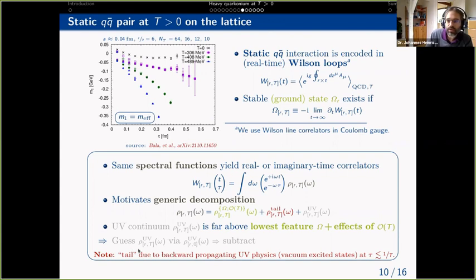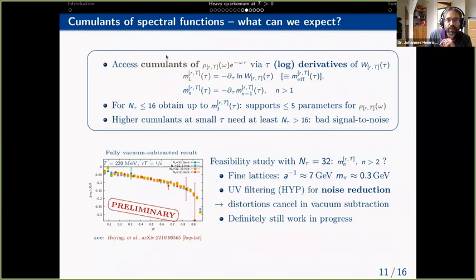For the UV contribution, we do the same thing that was done for non-relativistic bottomonium. So we estimate this from zero temperature and subtract it away. And then we are left with something that contains only this contribution, and the tail is what makes this bending down here happen. In this case, we can compute cumulants of the spectral function times the Laplace kernel over here.